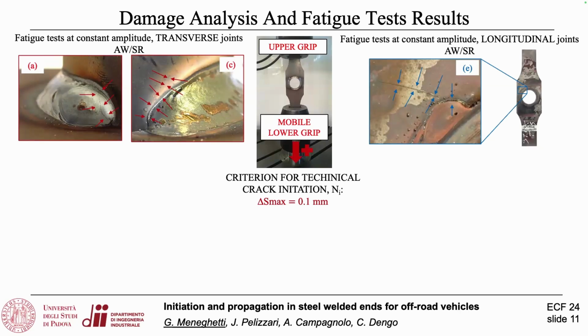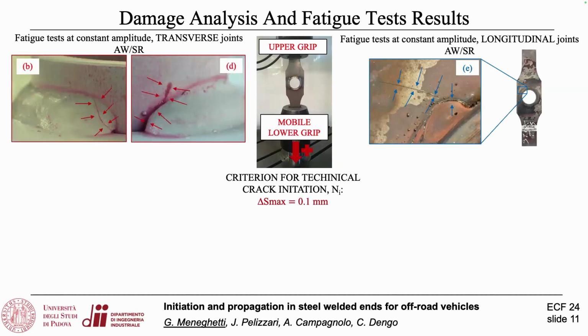You see here the tube. This is the plate. This is a crack emerged from the weld root, but at the same time, we observed some cracks at the weld toe. This is the weld toe, tube side. By using dye penetrant, you see better the initiated cracks.